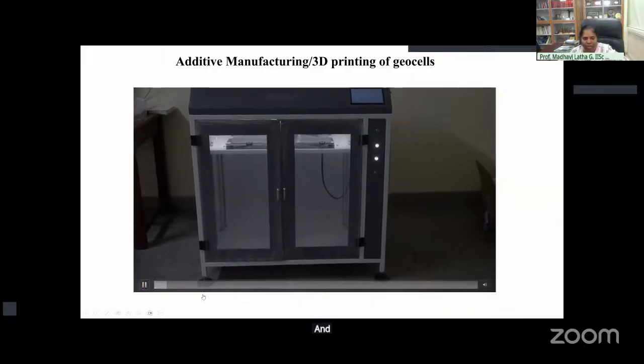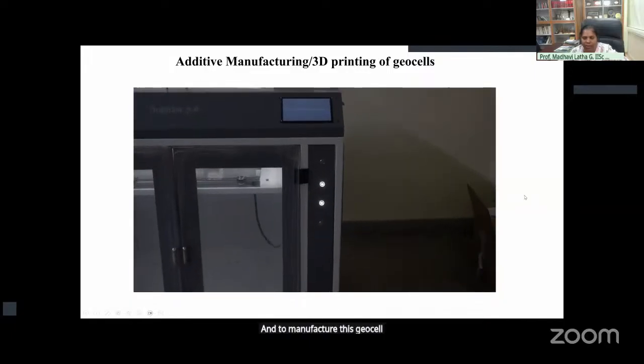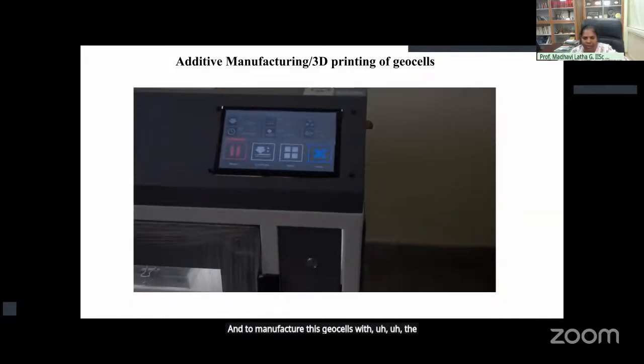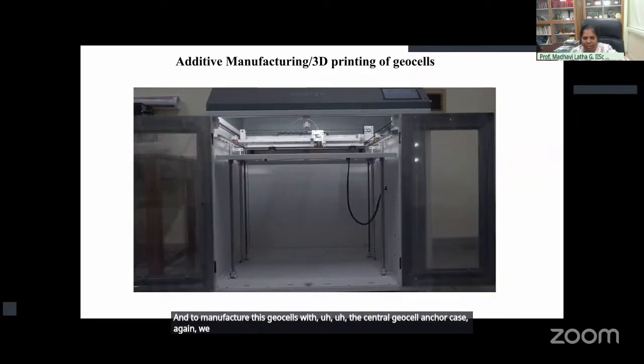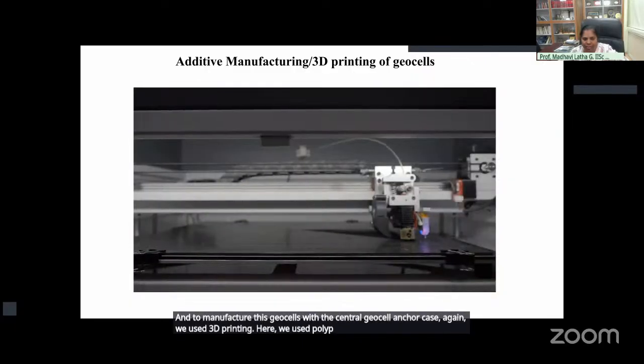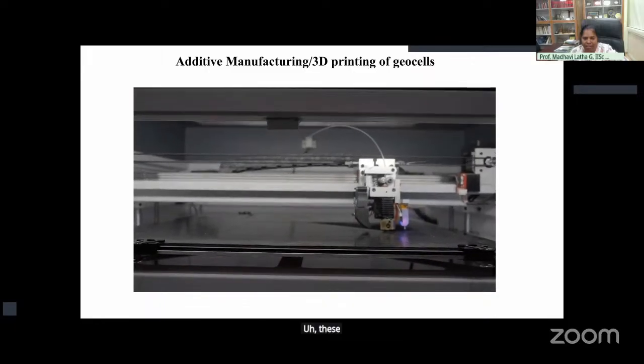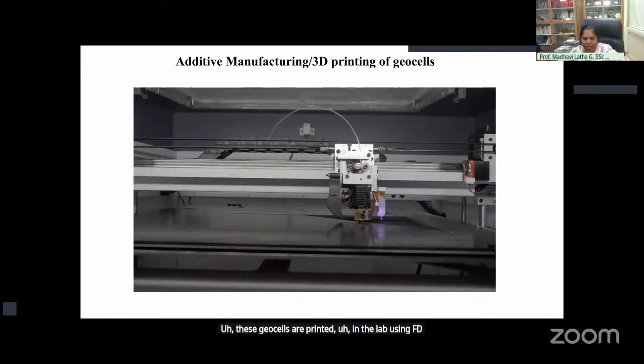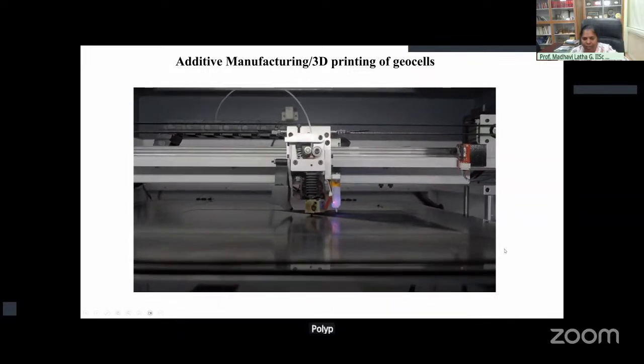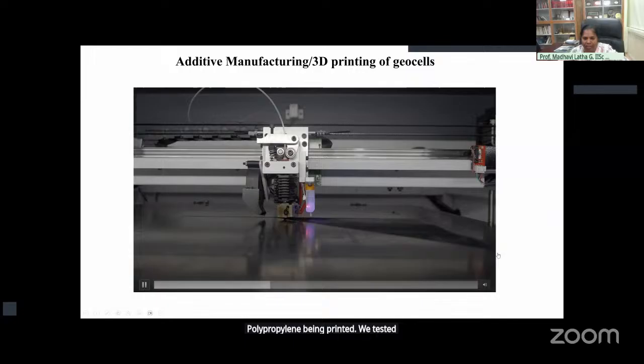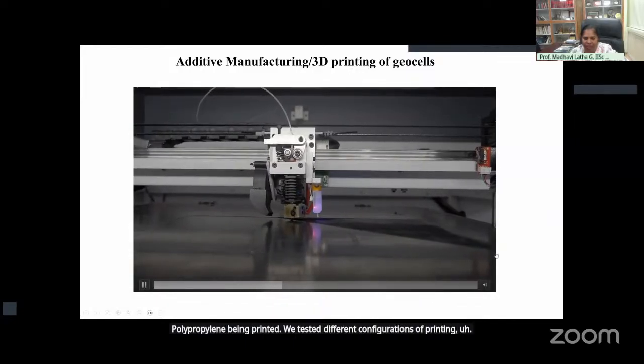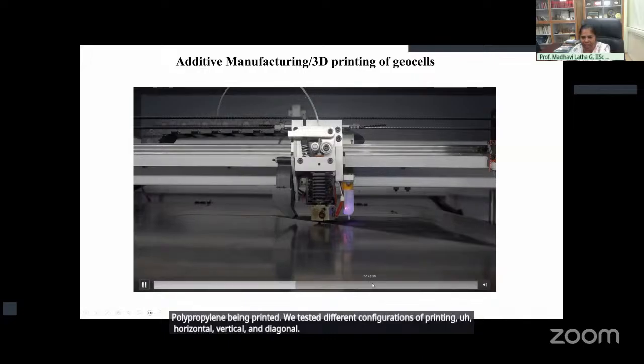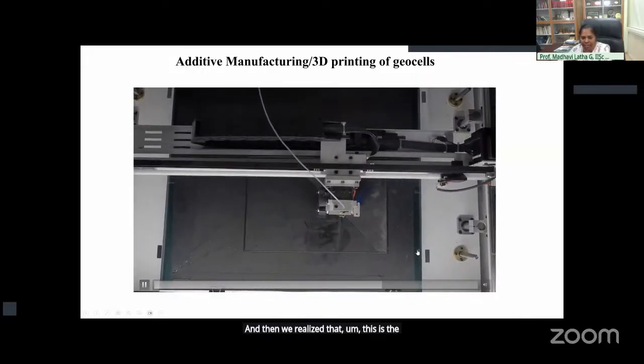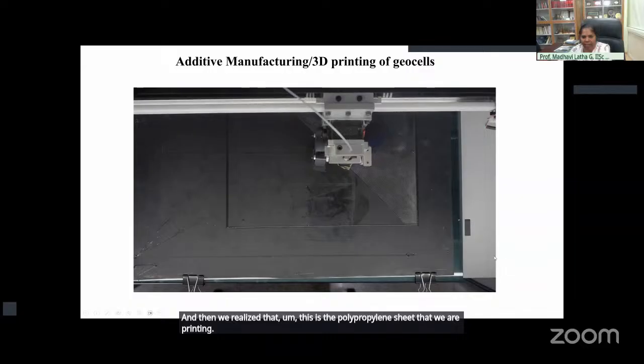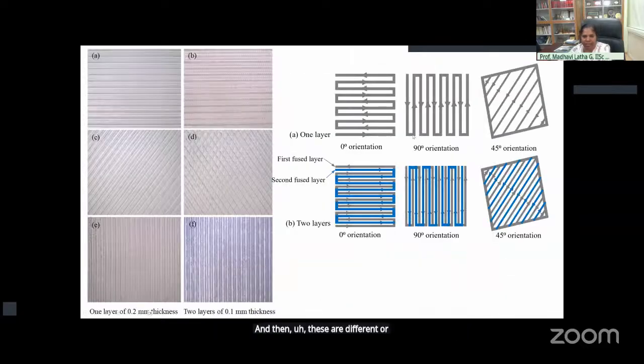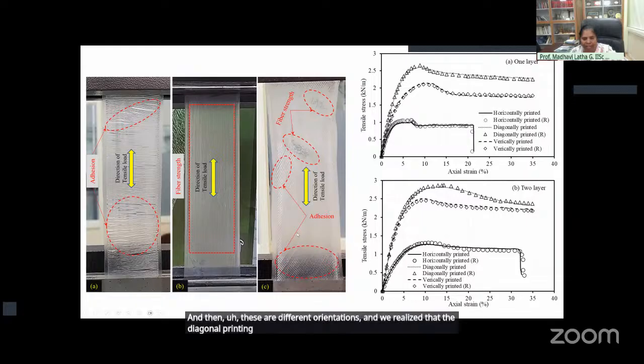And to manufacture these geocells with the central geocell anchor cage, again we used 3D printing. Here we used polypropylene to create geocells. These geocells are printed in the lab using FDM 3D printing. You are seeing the sheet of polypropylene being printed. We tested different configurations of printing: horizontal, vertical, and diagonal. And then these are different orientations, and we realized that the diagonal printing gives you the maximum tensile strength as